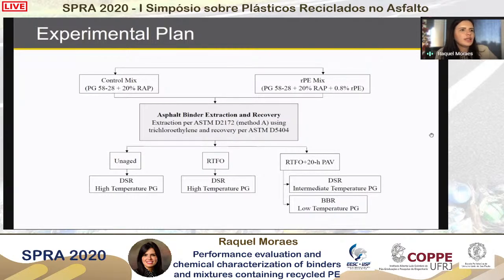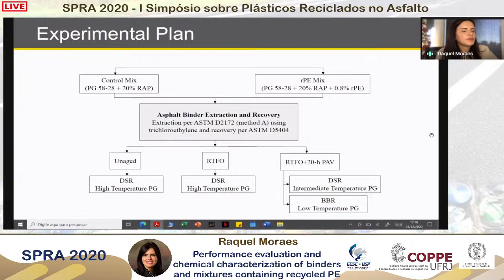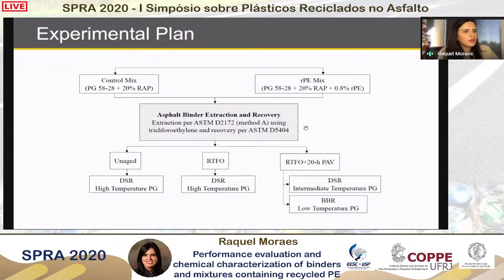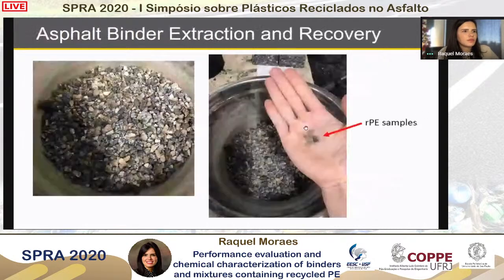And here what we did in this experiment: we have a control mix that was a PG58-28 binder that contains 20% RAP. And then we had a recycled polyethylene mix that contains a PG58-28 binder, 20% RAP, and 0.8% of recycled polyethylene. And from these two mixes, we used extraction and recovery to obtain the binder, and from the resulting binder, we evaluate the material as unaged, RTFO, and long-term aged on PAV, and I'm going to be discussing the results.